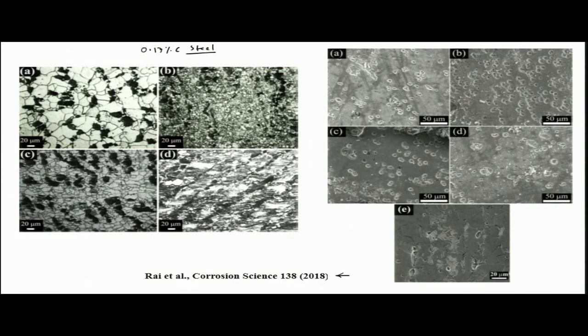The as-received structure had this particular microstructure with pearlite colonies — these are not called pearlite phase since they contain two constituents, ferrite and cementite; we call them pearlite colonies. The white portions bounded by grain boundaries represent ferrite alpha grains. This is the as-received 0.17% carbon steel, which was lightly rolled and air-cooled. Grain size is around 34–40 micrometers, as indicated by the micron bar.